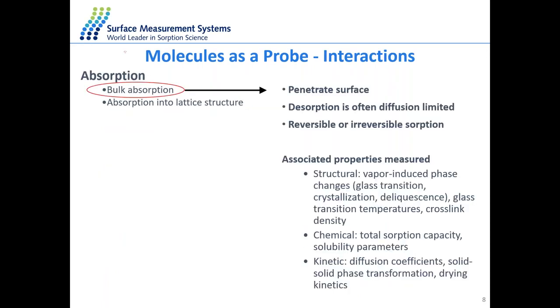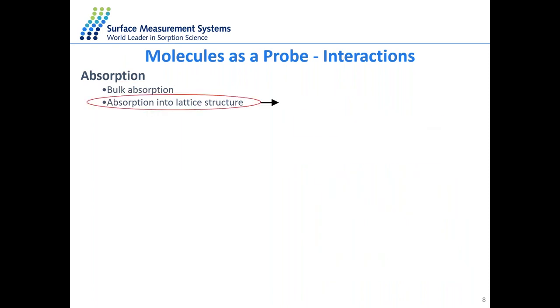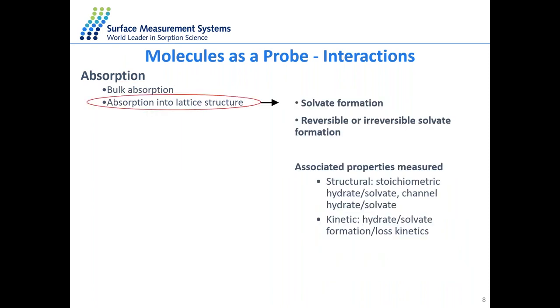So when molecules interact and go into the bulk of the material, we're actually looking at absorption. So we're able to penetrate into the lattice. And for this, it can be either reversible or irreversible. And in this case, because we're looking at bulk interactions, we can understand structural properties such as vapor-induced phase changes. And this is, for example, glass transition, crystallization, or deliquescence. We can also understand chemical properties such as total absorption and solubility parameters, and also kinetics such as diffusion coefficients and drying kinetics. When we're looking at absorption into the lattice, we can understand solvate formation. And this again can be reversible or irreversible. So we're looking at hydrate and solvate channels and understanding the kinetics.